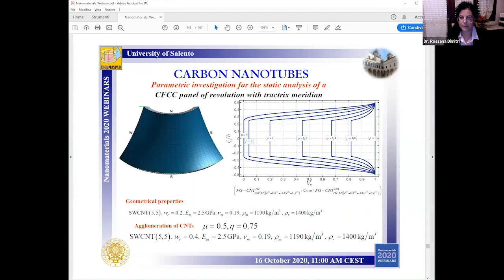So as a last example, we analyze a free-clamped doubly curved panel of revolution with a fixed meridian, made of 3 layers, subjected to a normal pressure on the bottom side and to a shear load on the top side. So both the external laminae and the core are reinforced by carbon nanotubes under agglomeration, with fixed mu equal to 0.5 and eta equal to 0.75. And the fixed mass fraction for the reinforcing phase is equal to 0.4. So in this case, also the 4-parameter power law distribution is applied symmetrically to the carbon nanotube volume fraction distribution to describe the through-the-thickness profile of the reinforcing phase, as you can see here.